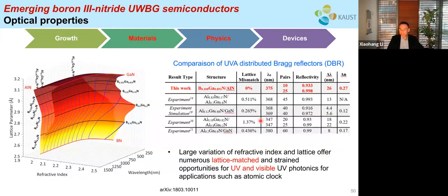In addition to electronic properties, which I talked about earlier, the optical properties of the boron 3-nitride are very interesting as well. So here we have a 3-dimensional figure showing the lattice parameter, refractive index, and the wavelengths for the boron, aluminum, gallium nitride materials. What is interesting is that we can get the so-called lattice matched heterojunction or superlattice from the boron 3-nitride